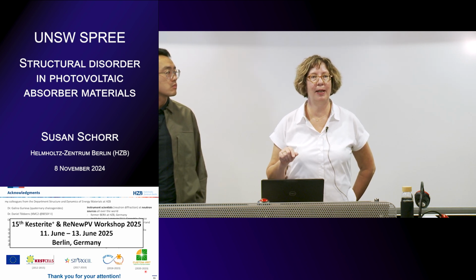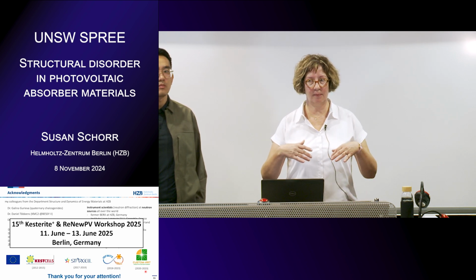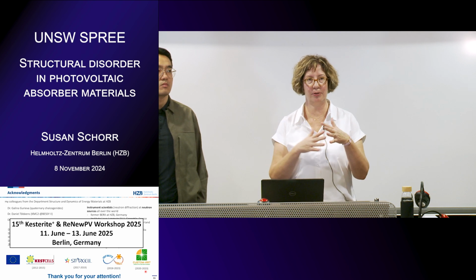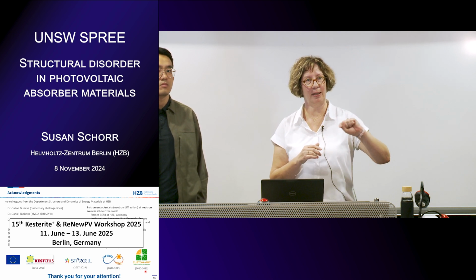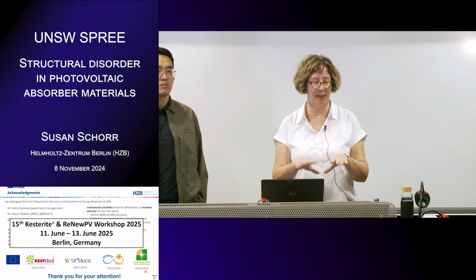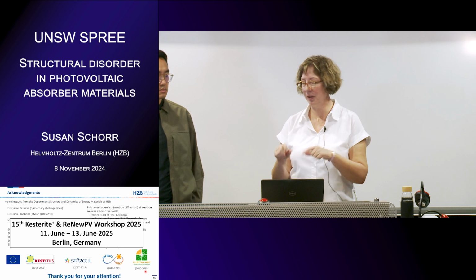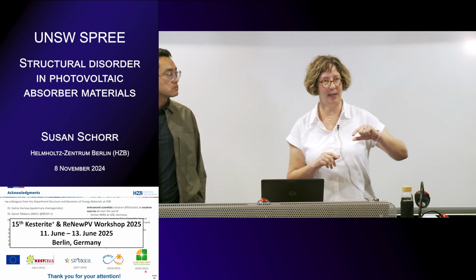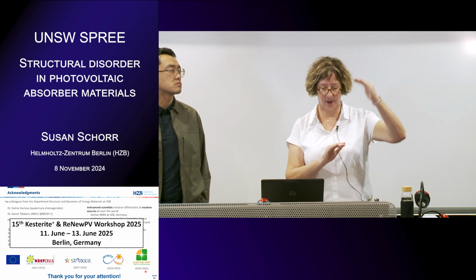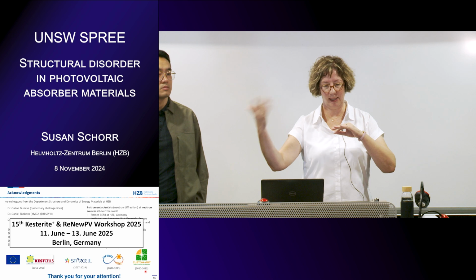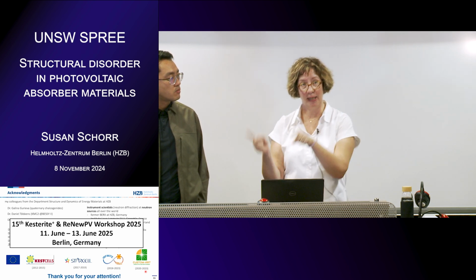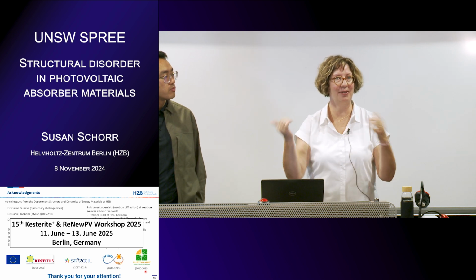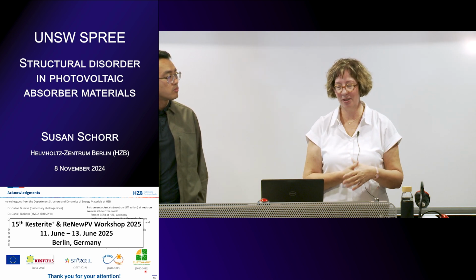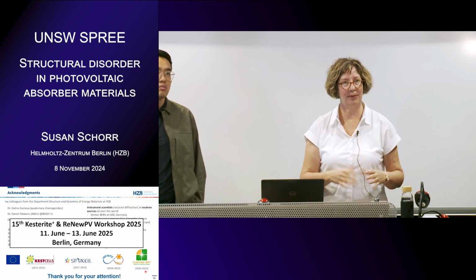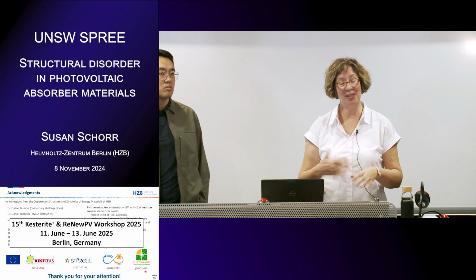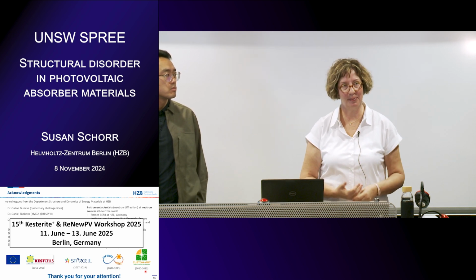For the kesterites, we don't have that, but for the chalcopyrites, there are these nice papers from Alex Zunger who calculated the defect levels in the chalcopyrites and also said which defect it should be. Because we have done the same work also on chalcopyrites, with the help of these papers, we could say, okay, we have this material with these defects, and according to the paper from Alex Zunger, it should be that level. Then we measured the PL, and we have seen these levels, and so we could correlate that. For kesterites, it's not so easy to get a good PL signal. They are very often quite low. So that's why we have this correlation for the chalcopyrites, but not for the kesterites.